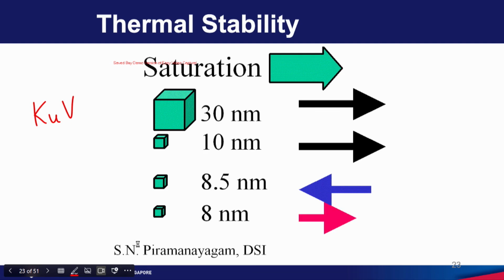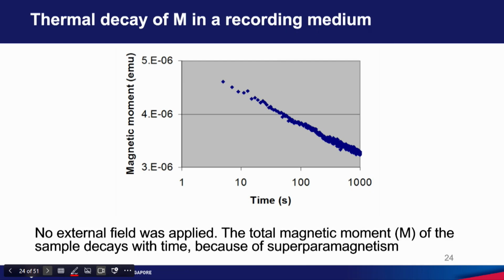So you will notice that when the volume is bigger, the magnetization is stable as a function of time, but as the volume gets smaller and smaller, the fluctuation frequency becomes more and more. So you can see 8 nanometer flips more rapidly than 8.5 nanometer cube of cobalt. So this problem is called thermal stability, and so even if you do not apply any magnetic field, the remnant magnetization might decay as a function of time. So in this measurement, even when there is no magnetic field, you can see that the magnetization decays as a function of time because of the competition between two energies, which are the anisotropy energy and thermal energy.